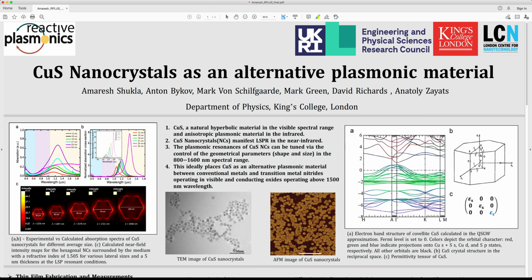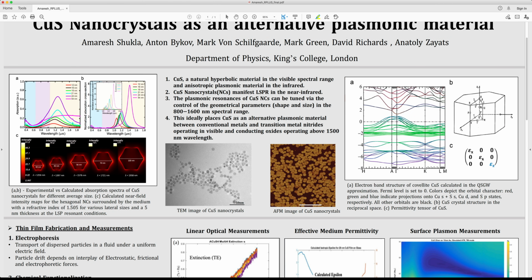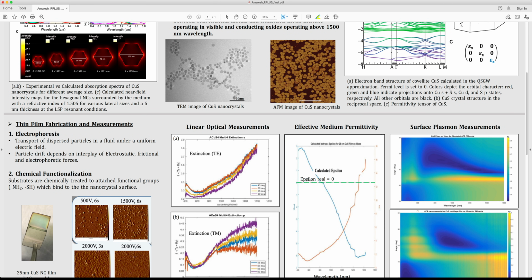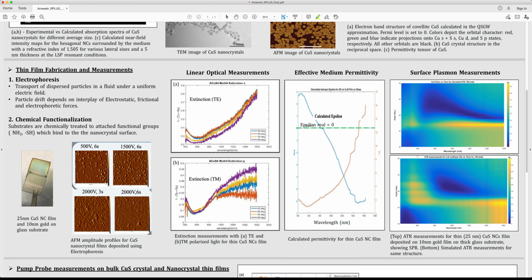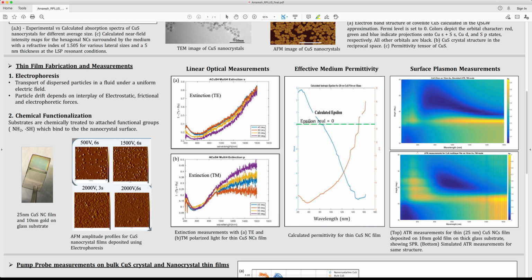In this poster, we further also demonstrate our study of large scale thin uniform films of copper sulfide nanocrystals. We use two very different methods of fabrication, one being electrophoretic deposition and the other using chemical functionalization of the substrate to bond with the nanoparticles. Through both these methods, we were able to make smooth, thin films which we then use for various optical characterizations.